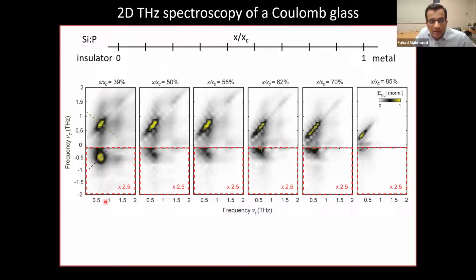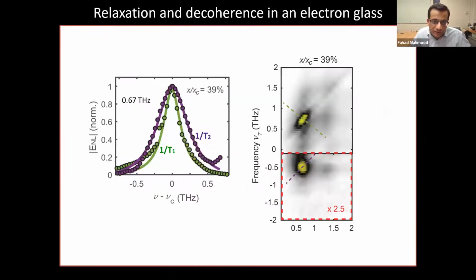So what I'm showing here is those 2D maps as a function of doping as you approach the metal insulator transition. What you immediately see is that as you approach the transition, all of these features get very, very sharp, okay? And what that means is that your lifetimes are essentially getting longer and longer, right? The scattering rate is decreasing, lifetimes are getting longer, okay? That makes sense, because if you just theoretically consider the hopping terms between two different phosphorus sites, that is usually exponentially suppressed in the phosphorus distance. But the Coulomb interactions are only algebraically suppressed. And so as you increase the density of phosphorus dopants, you're decreasing the ratio of interactions to hopping. And that's effectively making the system weakly interacting, which is causing these lifetimes to increase and sharpening the features that we see. Okay, so there's a lot of information in there on these maps.